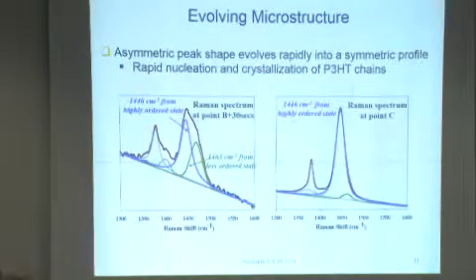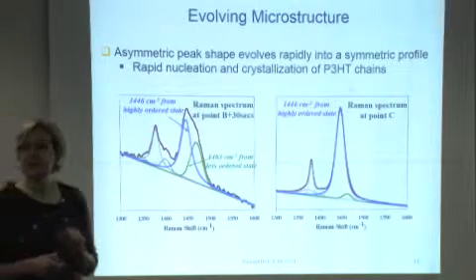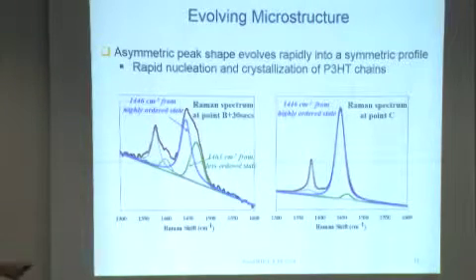All right, and we can look at the microstructure as the solvent's evaporating and deconvolute it. And basically, we start with a film that has both ordered and less ordered regions in it, and ultimately, at point C, have a largely ordered state spectrum. But then also from this point, as the film continues to evolve, there are additional changes taking place that we're trying to understand now.